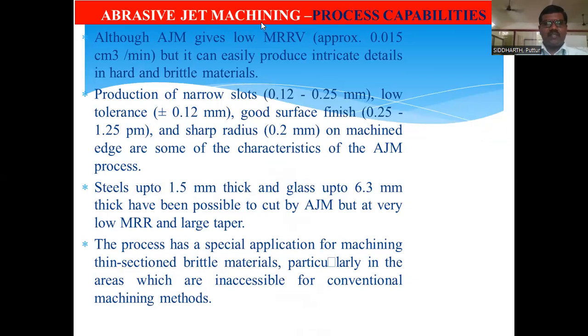Now coming to the process capabilities of abrasive jet machining. Although abrasive jet machining gives a low metal removal rate of approximately 0.015 cubic centimeter per minute, it can easily produce intricate details in hard and brittle materials. Even though the metal removal rate is less, it gives intricate details in hard and brittle materials which are not possible by conventional machining processes. The production of narrow slots such as 0.12 to 0.25 mm, low tolerance of plus or minus 0.12 mm, good surface finish of 0.25 to 1.25 micrometers and sharp radius of 0.2 mm on machined edges are some of the characteristics of the abrasive jet machining process.